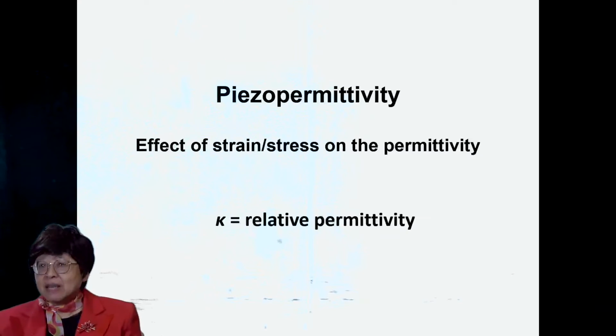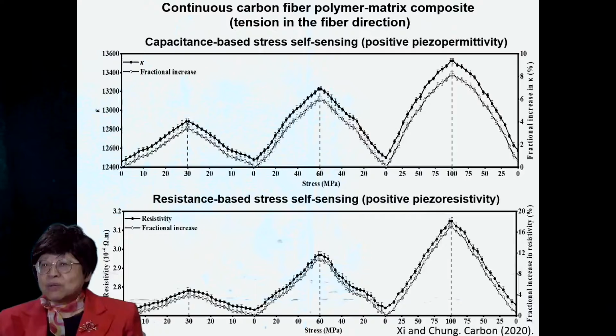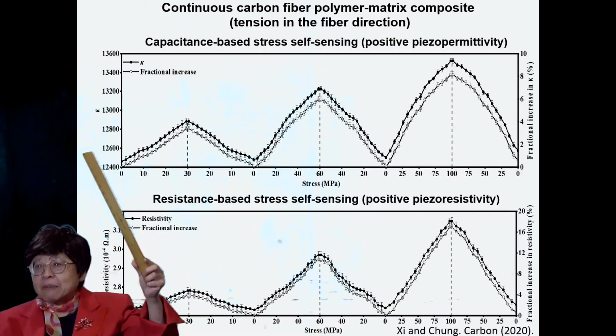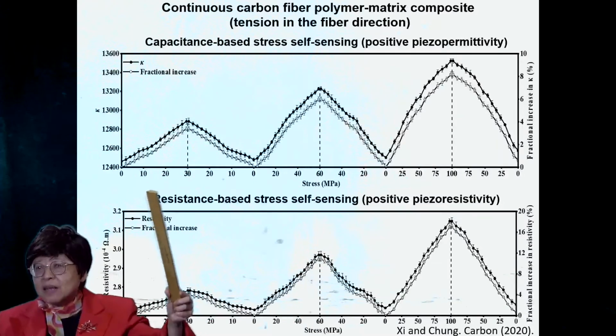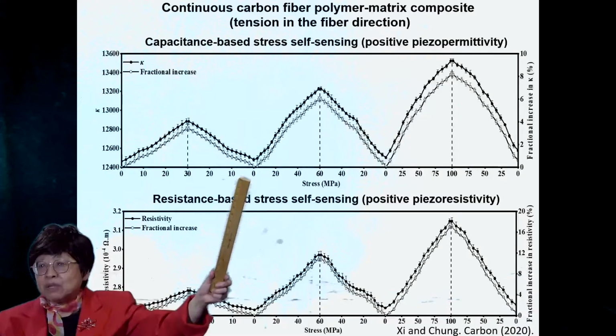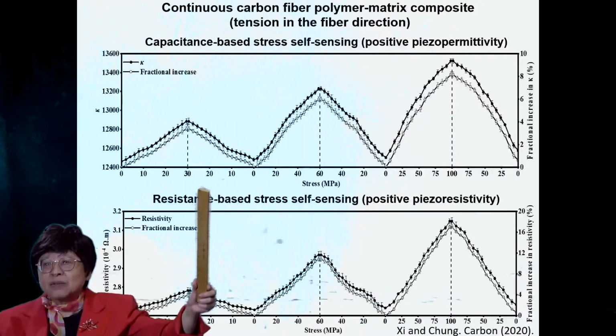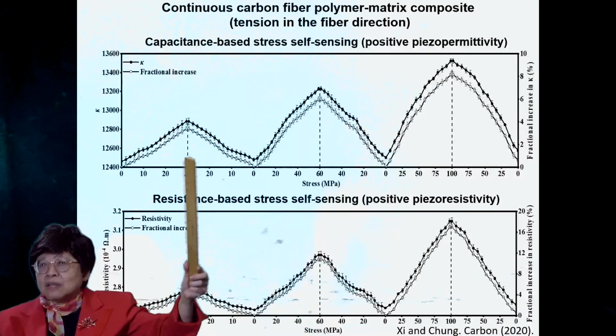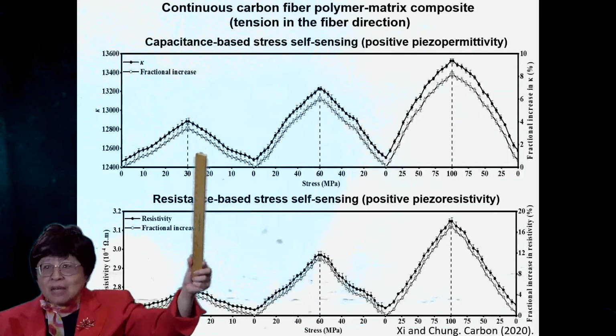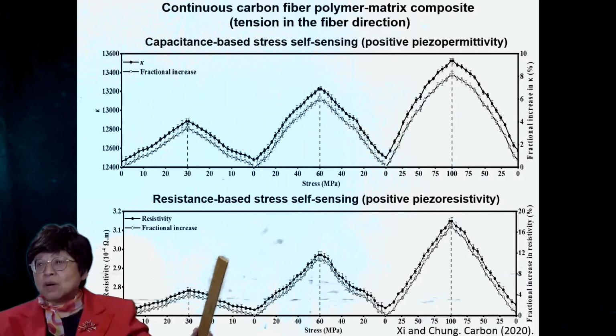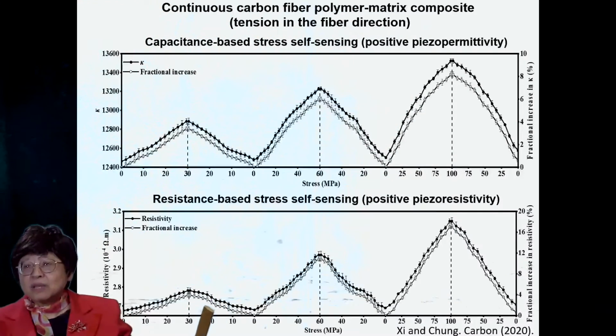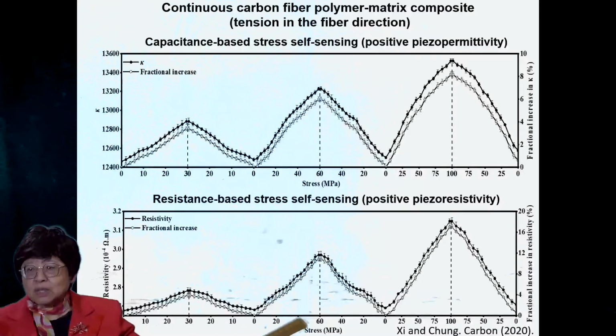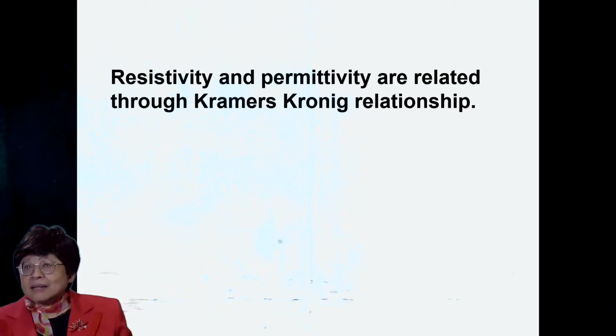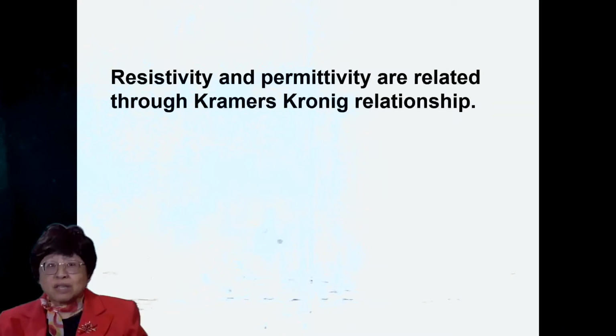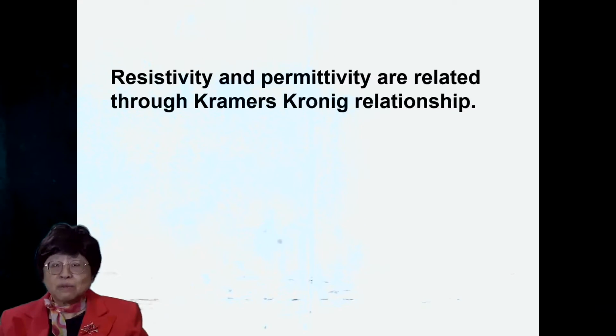Piezo permittivity means the effect of strain or stress on the permittivity. This shows the relative permittivity kappa versus the tensile stress at 3 different stress amplitudes, and the permittivity indeed increases reversibly. This is piezo permittivity. At the bottom is the same material showing the piezo resistivity, with the resistivity increasing quite reversibly upon tension. And the resistivity and permittivity are actually related through the Kramers-Kronig relationship.